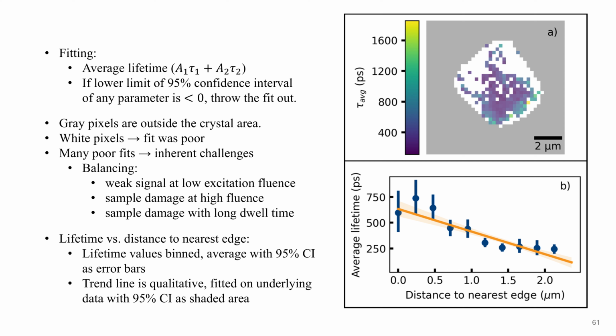And then the dot and the error bars here are showing the average and 95% confidence interval for that average of that bin. And then the line is really just a qualitative linear fit to give you an idea of the trend. But that's on the underlying data. It's not fitting the bins, it's fitting the underlying data. And there is a yellow shaded area that shows the 95% confidence interval. In this case, it's very close to the line. And the gray pixels are outside the crystal area that I determined with that little app.